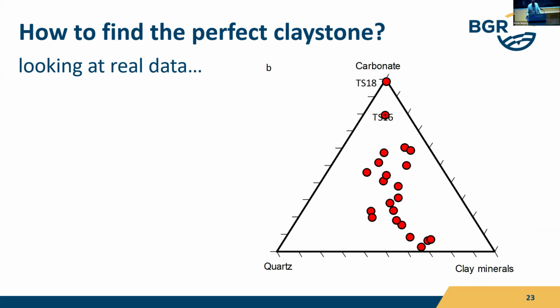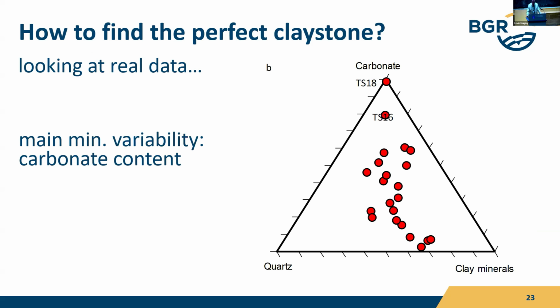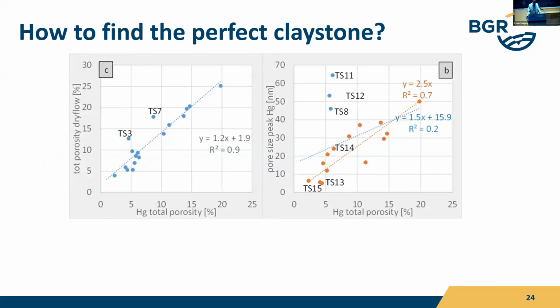Looking at real data. So first, the modal mineralogy. This is just calculated based on chemical composition, but this is enough to see that the variability is the carbonate content. That means in the sample set, the quartz to clay mineral content is more or less constant, right? There's a certain range, but in real systems, you will find an even more significant range. But typically, the carbonate content is the parameter which really has the highest variability in case of claystones.